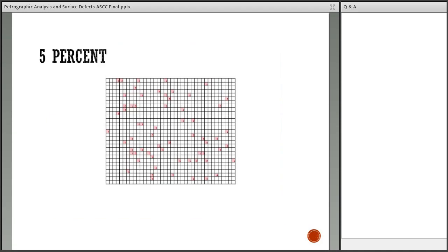Getting back to some sampling issues, especially with pop-outs, this is a randomly generated pattern for 5% particles. You can see, let's just say they're opaline shale particles. Basically, you can see 5% with a random pattern, you get quite a bit across the whole area.